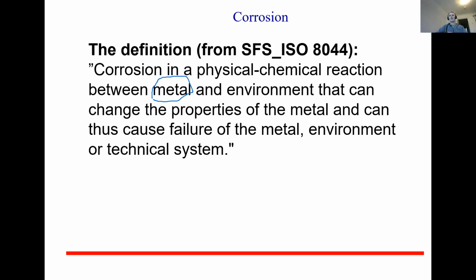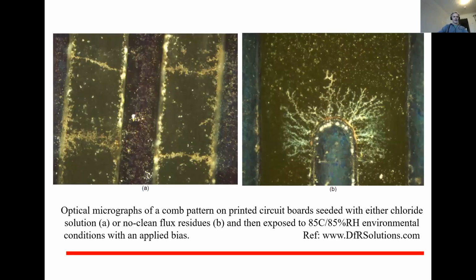So first thing was the metal, and then the effects of these electrochemical reactions you should look at from different viewpoints. So here is one example. Maybe not that clear a micrograph, but these dark ones are copper tracks on a printed circuit board, and this greenish stuff is the spacing between the copper tracks, and these have been tested in different conditions, chloride conditions, and conditions where there are flux residues, so soldering fluxes. And what is observed is that dendrites, these tree-looking structures, have started to grow. And of course, here and here, we have a short circuit.